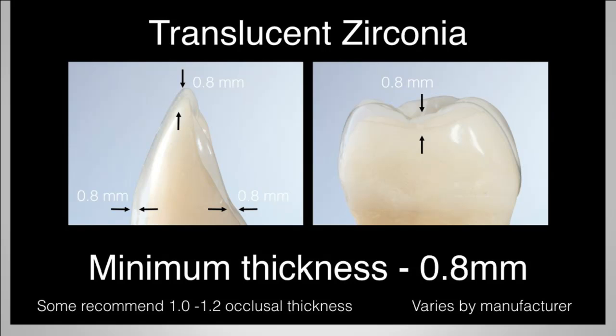I believe in conservation of tooth structure, but I also want to be cognizant that we don't want to push the envelope too much where fractures can occur. The most common area of fracture can be the central groove. The central groove becomes an area that, as clinicians, we tend to get under-reduced. At the same time, we ask our laboratory for beautiful anatomy. So if we don't quite give them enough room, yet we ask for beautiful anatomy, the central groove can get quite thin. My recommendation would be for translucent zirconias, really consider at least a millimeter of occlusal thickness, maybe up to about 1.2 millimeters of occlusal thickness. And that's what I would really feel more comfortable doing with these translucent materials.